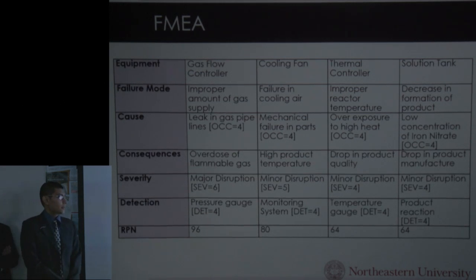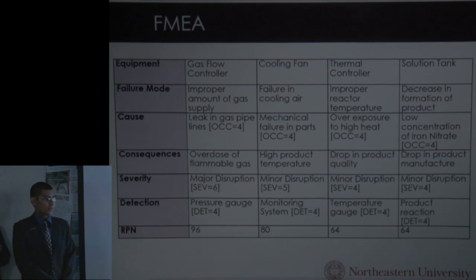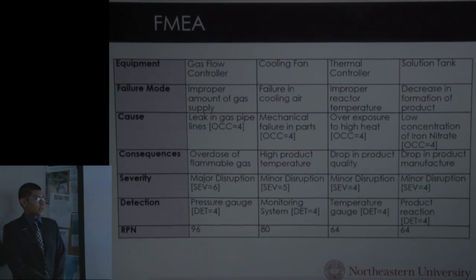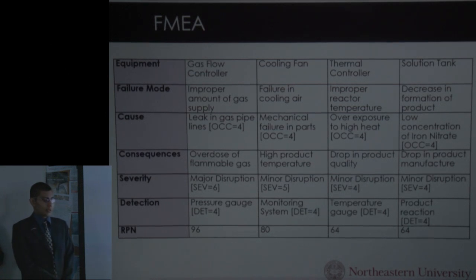Next is the cooling fan. The substrate of copper and graphene formed in the tube furnace is at a temperature of 1000 degrees Celsius. So coming out of the furnace, the substrate is very hot. We want to reduce that temperature as low as possible because the substrate goes into the solution tank where iron nitrate solution is present. We do not want high heat entering the solution causing unfavorable reaction.